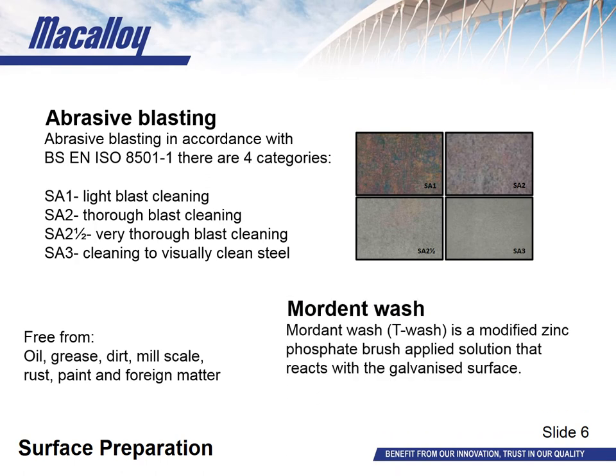Preparing galvanised products post-galvanising follows a slightly different process. When preparing galvanised products for additional coats such as paint, T-Wash is considered to be the best pre-treatment process. T-Wash or mordant wash is a modified zinc phosphate solution which contains a small amount of copper salts. When applied, a dark grey or black discolouration of zinc will result. An alternative to T-Wash would be sweep blasting, however it's uncommon at Macalloy so we decided not to talk about it.